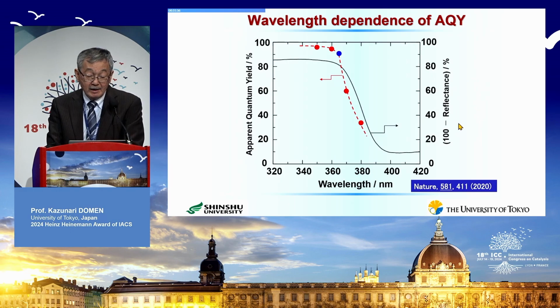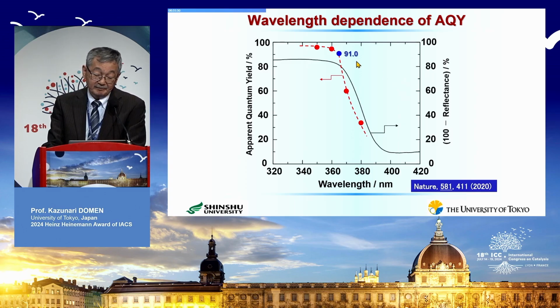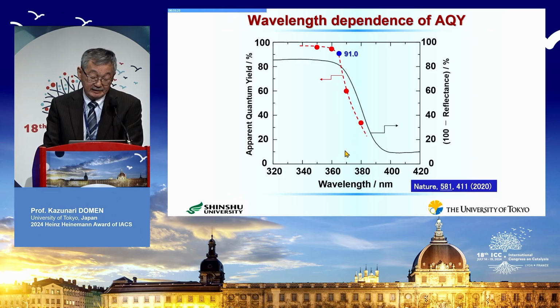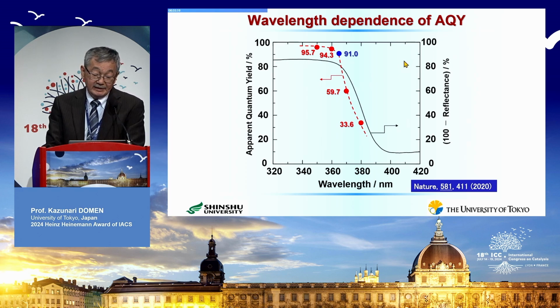Here I show the wavelength dependence of this apparent quantum yield of this photocatalyst, and this is the data that I showed in the previous slide at 365 nanometers. We also measured at different wavelengths, as shown here. In our case, this apparent quantum yield is defined based on the total photon number which was introduced into our reactor. That means that some small portion of the introduced photons are scattered out without being absorbed by our photocatalyst.